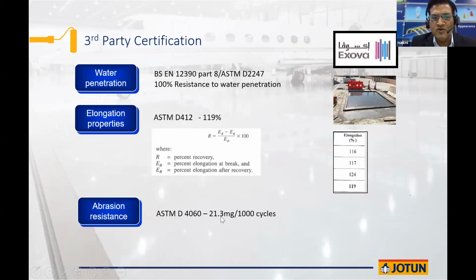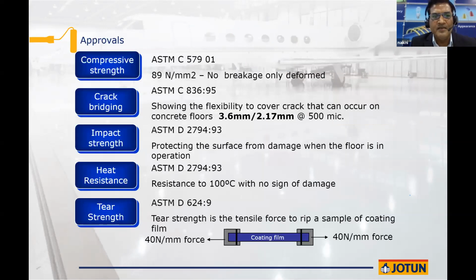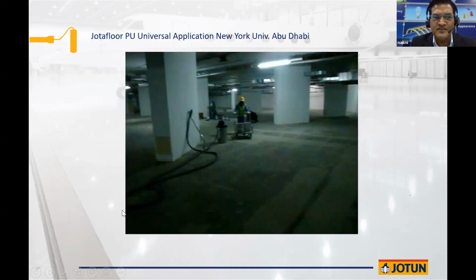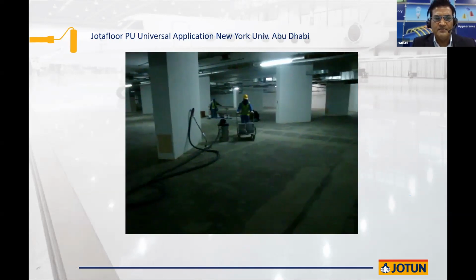That means almost double the standard that is required, that is specified in the ASTM C579-01 standard. Compressive strength of 89 Newton, almost 3 times concrete. Crack bridging ability of 3.6 and 2.17, depending on the DFT. Impact, heat resistance, tear strength. And I would like to show you a video of a real-time application of this product on Abu Dhabi's New York University.